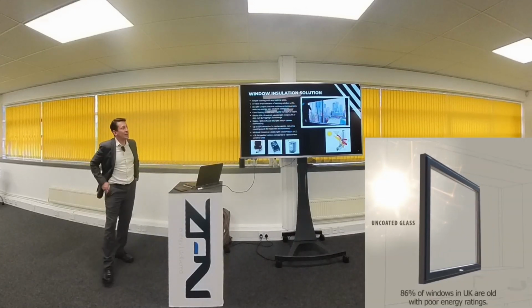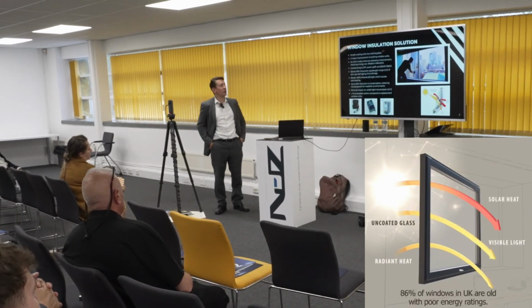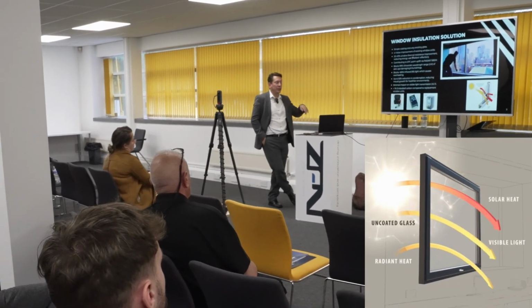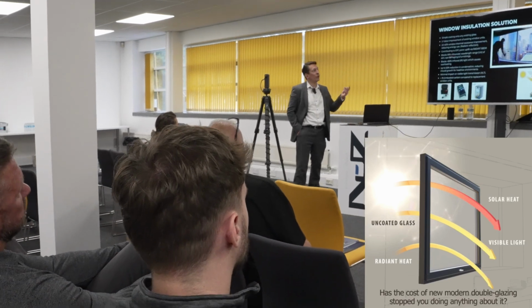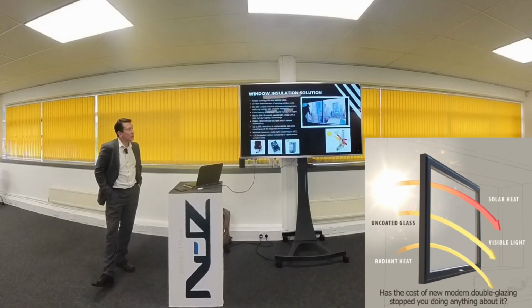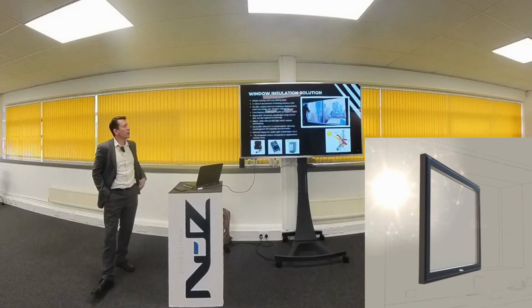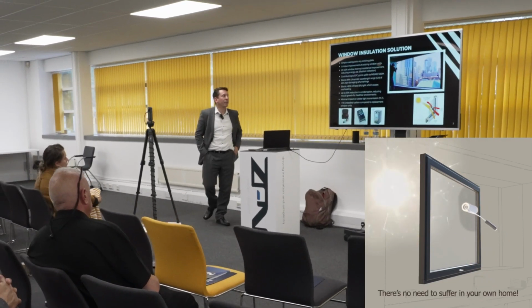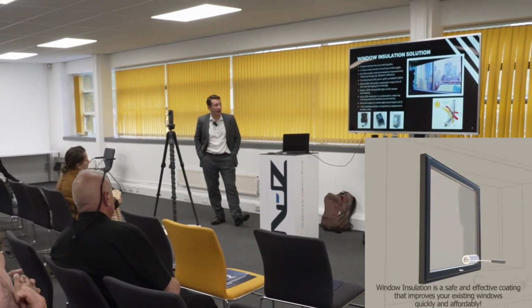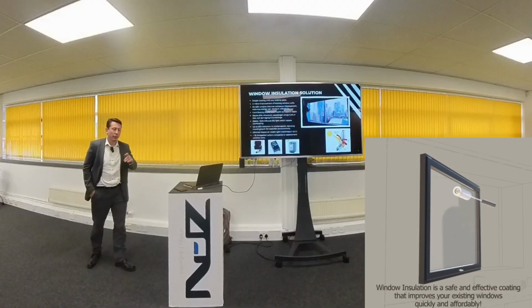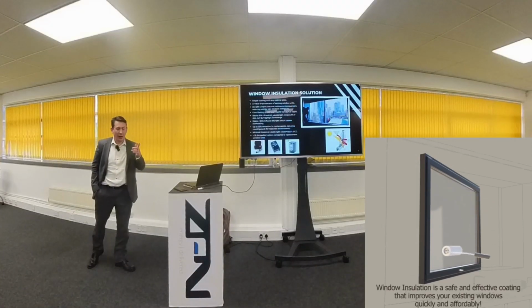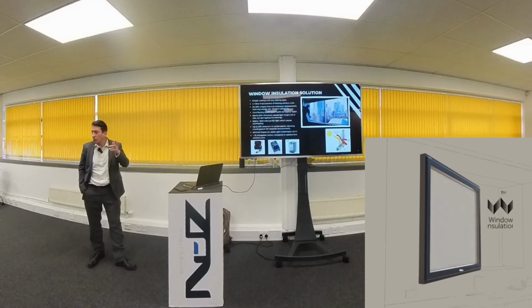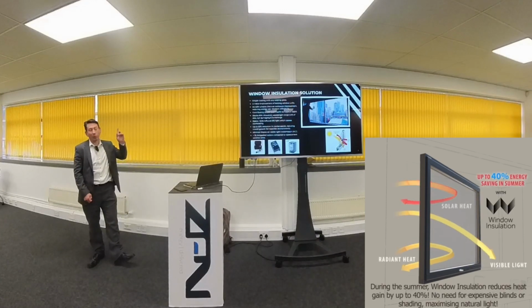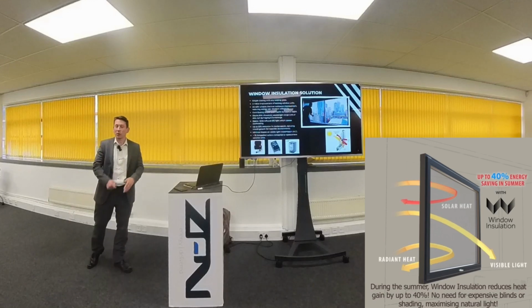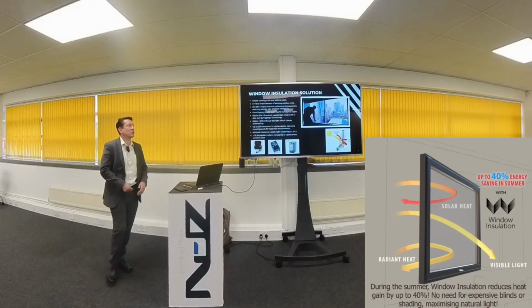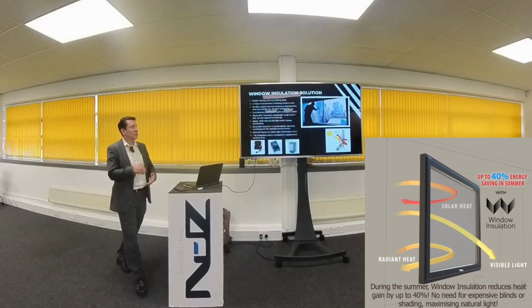It goes onto any glass, U-value improvements onto existing windows, 20% energy saving through the glass in winter, 40% in the summer, contributes to EPC point improvements. It blocks 99% of UV, which causes damage to skin, eye and furnishings. And to give you an idea, 4mm heritage glass, single pane, cuts about 15% of UV. This, when applied to heritage glass, cuts 99%. So it stops things from fading, stops skin and eye damage risk.